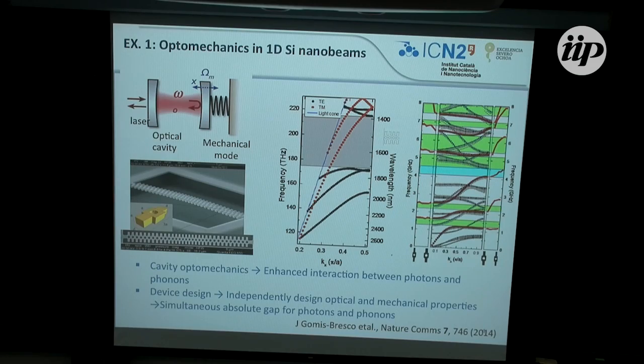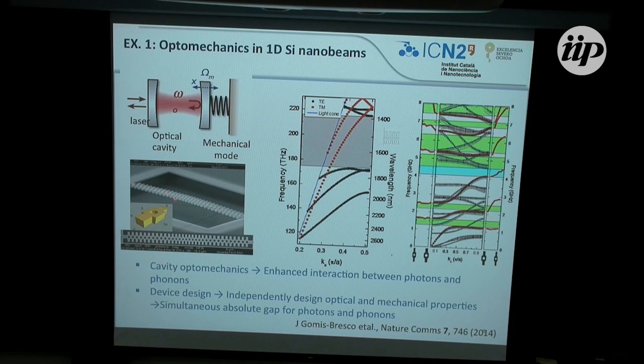And so this picks up certain resonances when they couple, and others are induced by bringing light through an optical fiber, coupling the light modes to the photonic modes, which in turn couple to the phononic or mechanical modes in the system. And the light that is transmitted is our signal that enables us to study the phonon-photon interaction. Most experiments until we started work in this area were performed at very low temperatures, 4 Kelvin and so on. And we decided to put up with real life, which I think is quite a challenge, but why not? It stands a better chance of being used. And we work at room temperature, and we decided to stick to silicon for obvious reasons. When you have to make these structures, reproducibility plays a tremendous role, and you have to have a means to repeat the structure and make it again.